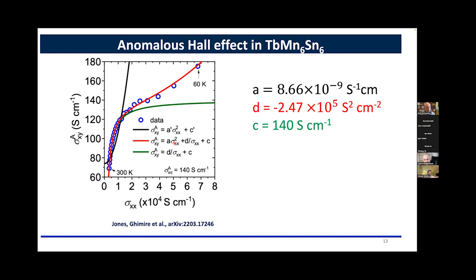Another thing is that the A sigma XX square term is not that important at higher temperatures. If you just remove this A sigma XX square term and plot this fit equation, at high temperature the fit is pretty good, the red and green one. But it deviates only at lower temperature. And remember, at lower temperature there can be a contribution from this A, which is very obvious.